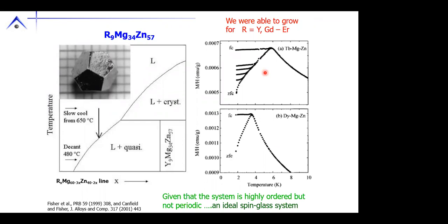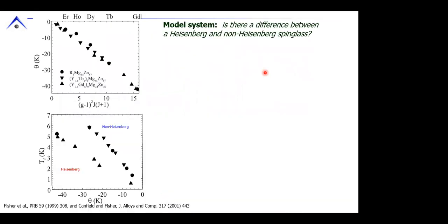Okay? Now, if I end up saying something's a model system, it's fair to say, well, then use it to ask very clear or clean questions. And with these materials, we were able to ask the question of, is there a difference between a Heisenberg and non-Heisenberg spin glass? So we looked at the rare earth magnesium zinc for erbium, holmium, dysprosium, terbium, gadolinium, and two dilutions, yttrium terbium and yttrium gadolinium. If we look at the paramagnetic theta value, we can scale this with the de Gennes factor, and we can see beautiful linear behavior, which is exactly what you would hope for and anticipate.